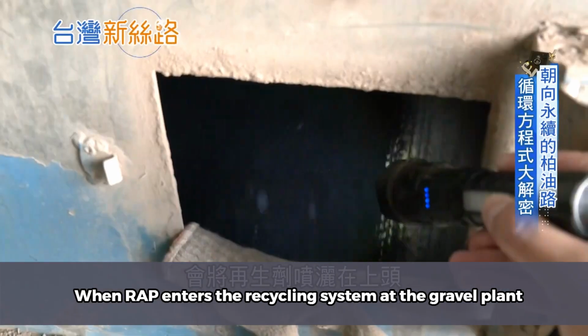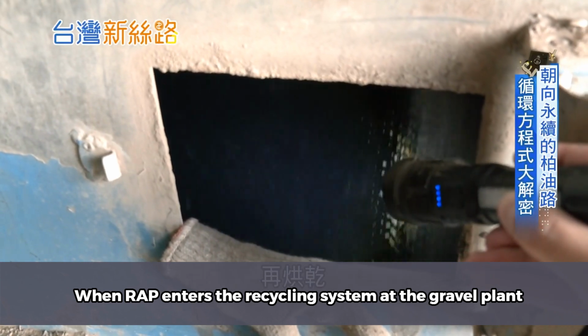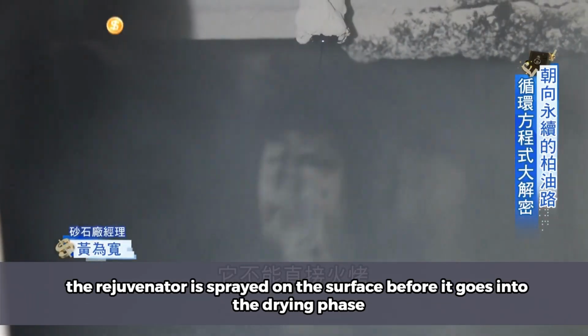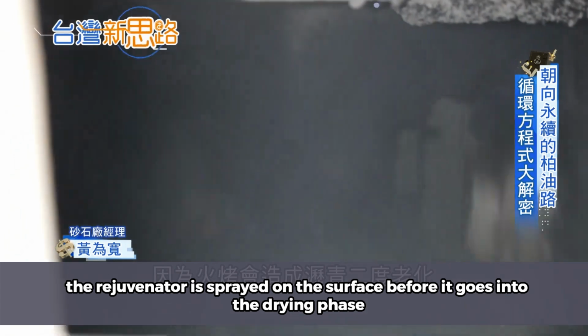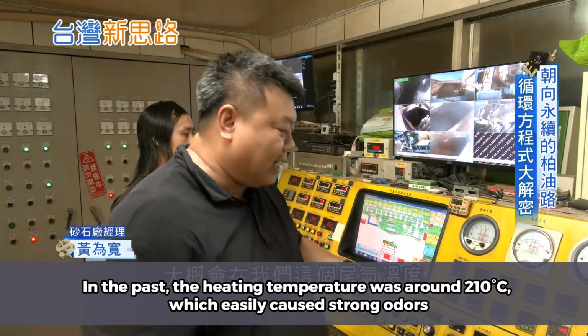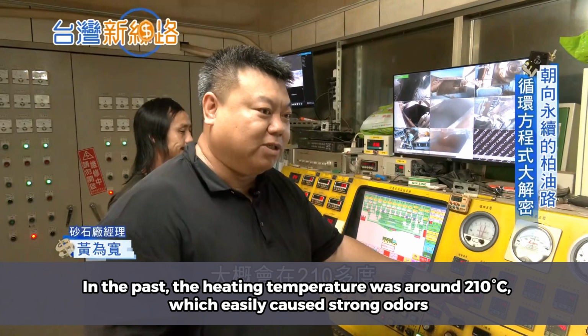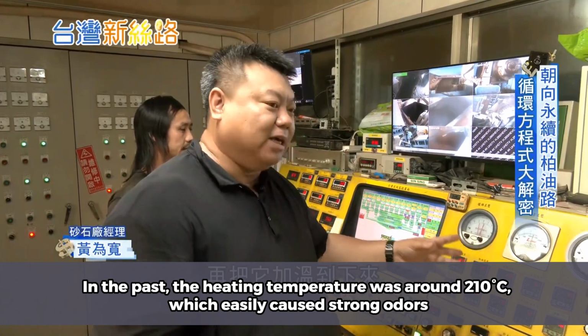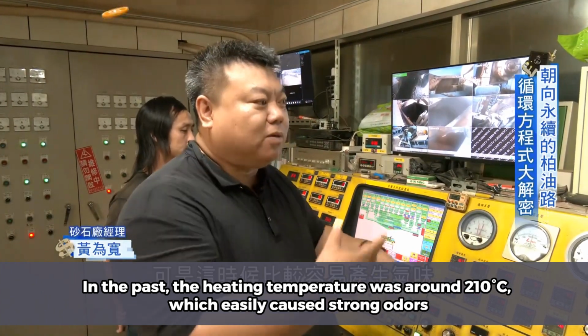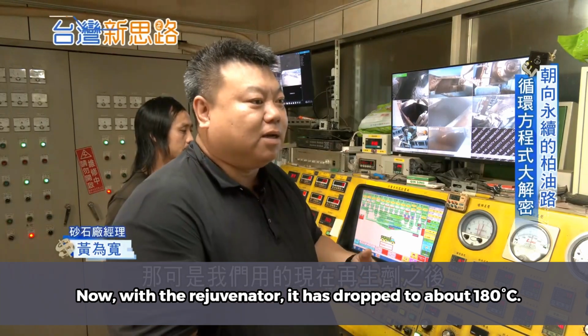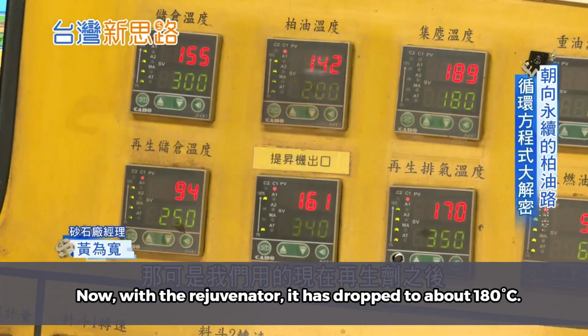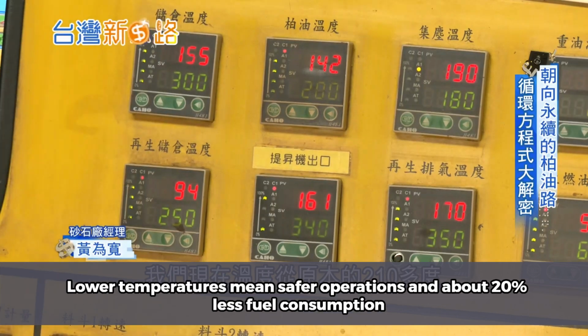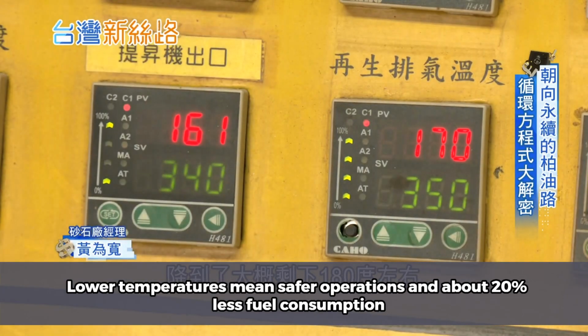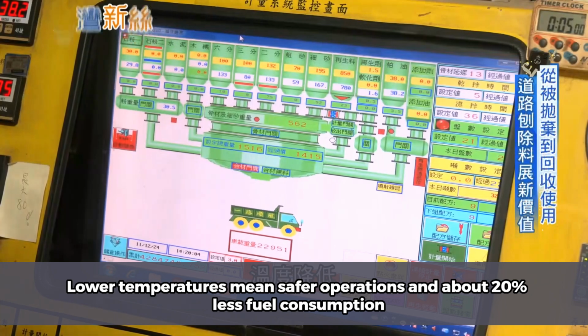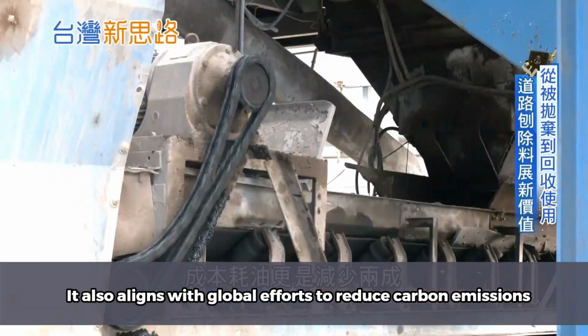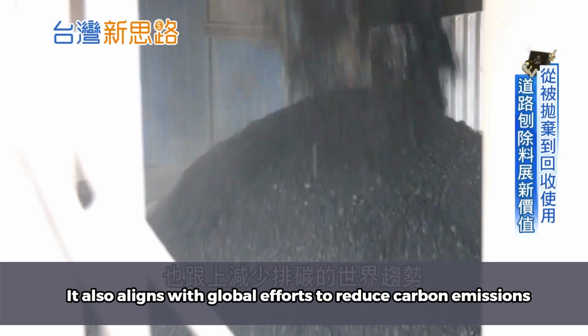When RAP enters the recycling system at the gravel plant, the rejuvenator is sprayed on the surface before it goes into the drying phase. In the past, the heating temperature was around 210 degrees Celsius, which easily caused strong odors. Now, with the rejuvenator, it has dropped to about 180 degrees Celsius. Lower temperatures mean safer operations and about 20% less fuel consumption. It also aligns with global efforts to reduce carbon emissions.